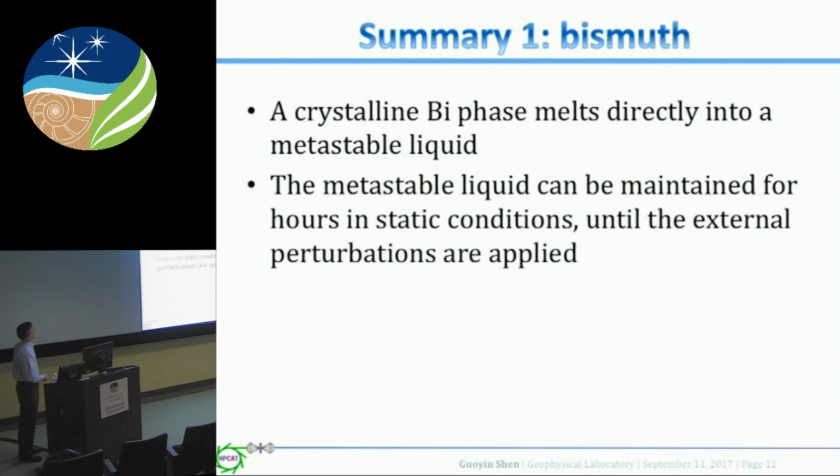So just a brief summary for this bismuth sample. We found that a crystalline bismuth phase melts directly into a metastable liquid. This metastable liquid can be maintained for hours. We can maintain it until an external perturbation is applied. So that's what we observed for bismuth.